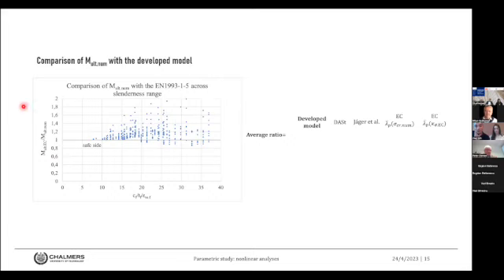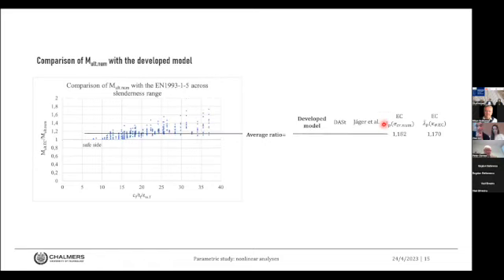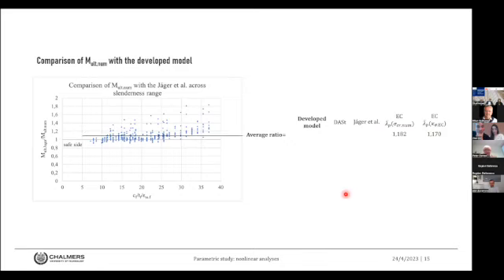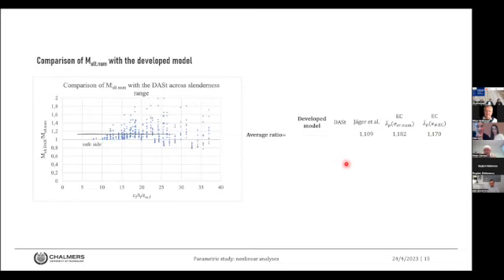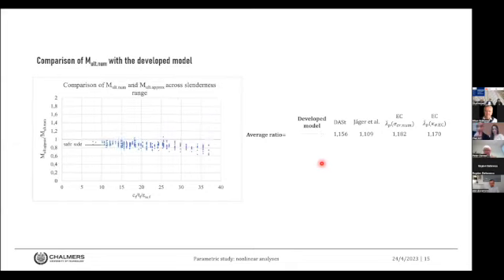So finally, we summarize the comparisons of the different models with regard to ultimate moment capacities, starting with the Eurocode, using lambda as a function of the buckling coefficient given in the Eurocode itself, and then using lambda as a function of the critical stresses obtained from finite element results. The model of Jaeger et al., proceeding with the DASt-Richtlinie 015. And lastly, the developed model with an average underestimation of 13.9%. And here are the standard deviations of all models compared to each other, just for reference.